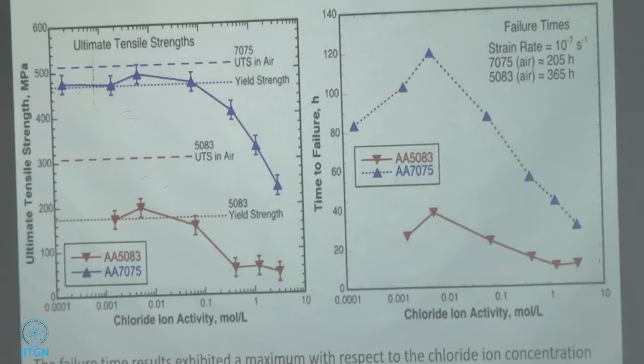And here are the failure times. So basically, this is strain rate at 10 to the minus 7. It takes a long time to do a test at 10 to the minus 7. Many of the tensile tests that we do in the laboratory are 10 to the minus 3 per second. That's the strain rate that we normally use when we do a tensile test.